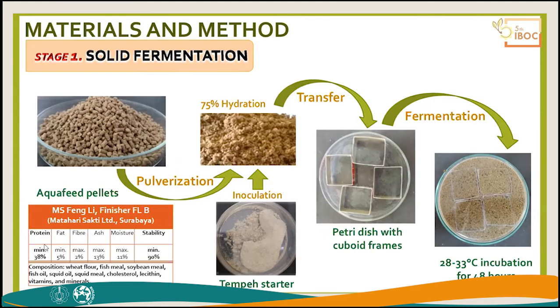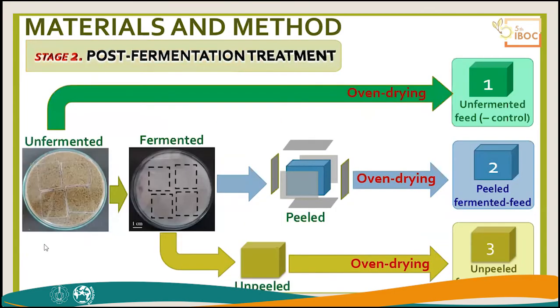And then after we mix homogeneously, we transfer it into a petri dish, inside of which we have rectangular shape frames, and we incubate at about 28 to 33 degrees centigrade for 48 hours. After the fermentation, we get the fermented sinking feed like the one in the picture. We see the surface of the petri dish was covered by a cotton-like structure. So it indicated that the fungi, normally Rhizopus, grew very well.